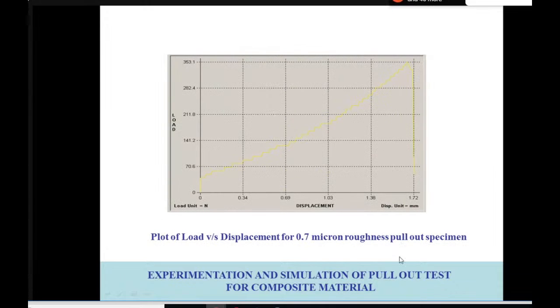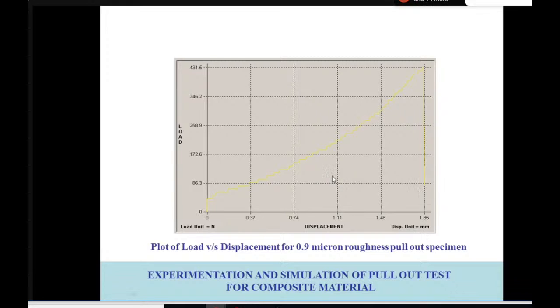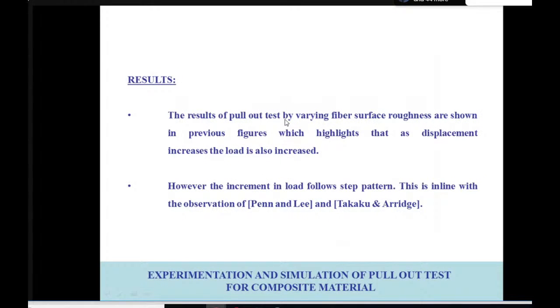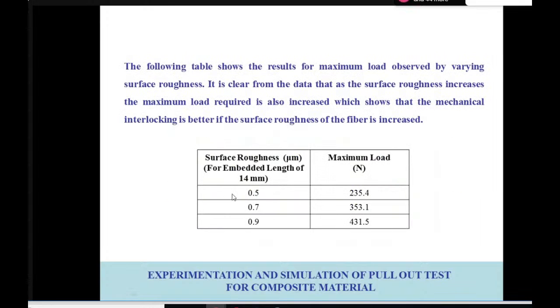Similarly, this is for 0.7 micron roughness. You can see this zigzag. This zigzag means whatever emery paper roughness you have applied onto the rod, at every instant you will feel a resistance. That is why this peak and valley has happened. Then after a certain period, it falls down. Similarly here for 0.9, it has moved like this up to here and then a sudden failure. This is how you can see the failure results. Now look at the table: when you go for a bigger size of emery paper, more roughness, you get these readings. So for 0.5, 0.7, 0.9, the load required to pull the rod from the polymeric ring is increasing.